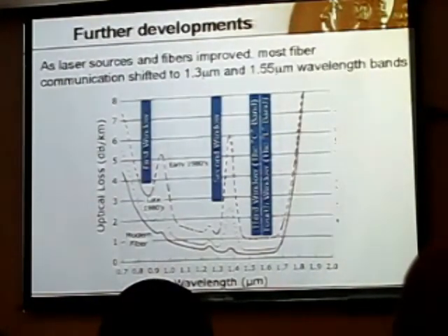Now, what is the situation today? So that is what is figured out. Eventually, laser sources shifted not to 633, the red lasers, but today all optical communication is either around 1.3 microns or 1.5 microns, where the loss of the glass is the minimum. Actually, you're still dominated by the tail of some other water vapor band somewhere which you can't avoid anyway, or the SiO band. So you operate at losses much less than 1 dB per kilometer.